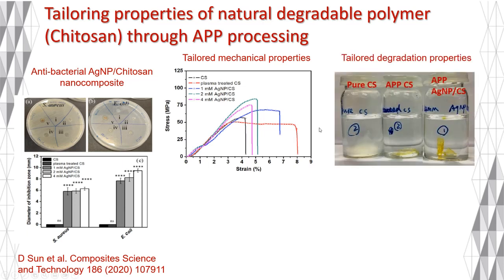For example, this can be seen from the stress strain curves. A mere 5 minute treatment with the plasma can remarkably enhance the toughness and ductility of the neat chitosan film. And additionally, the water sensitivity of the chitosan has been altered due to the cross-linking induced by the plasma chemistry. So as shown in this photo here, the previously highly soluble polymer chitosan can now achieve a much better stability in water. And it's possible to tailor its degradation profile by adjusting the plasma processing parameters.